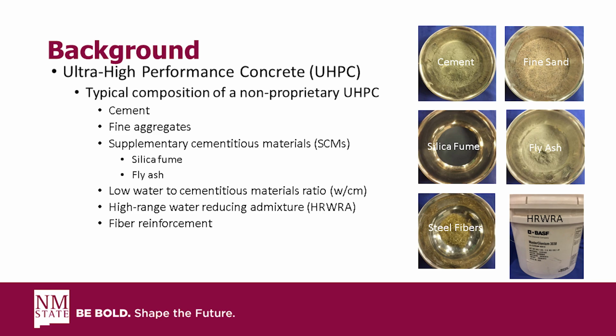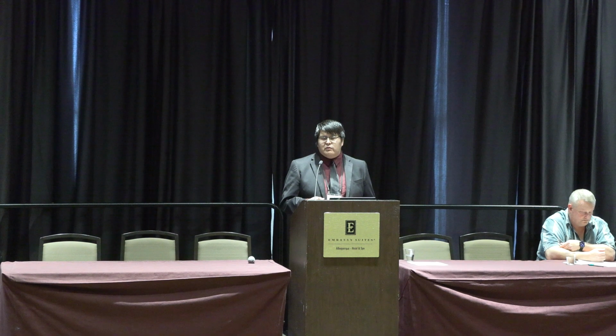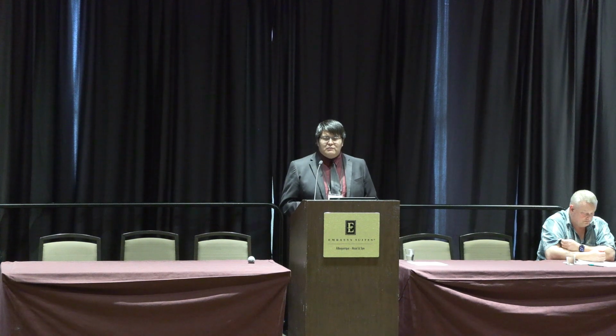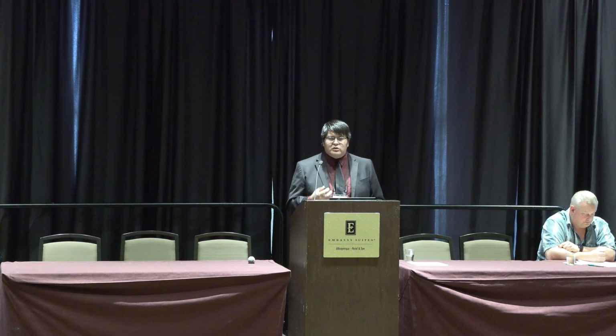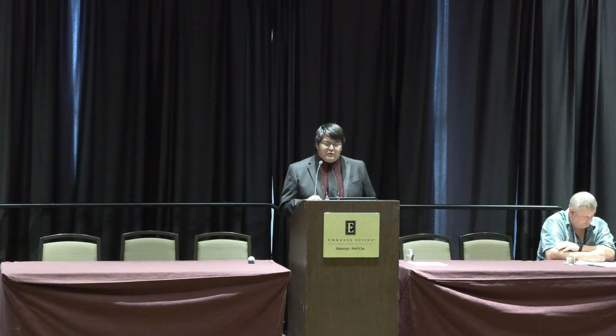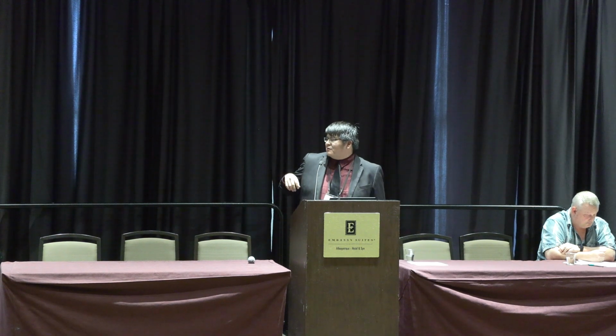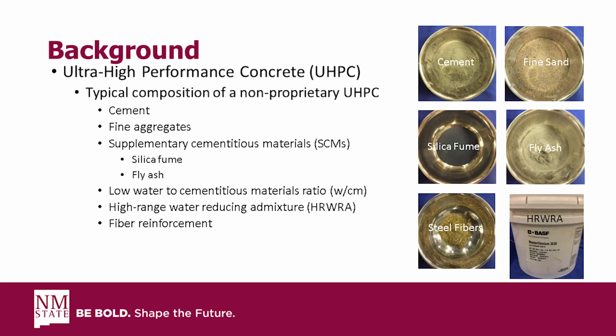Okay, and we have a low water to cementitious materials ratio, typically around 0.13 to about 0.16 is what we're looking at. And to have that low of a water to cementitious materials ratio, we need to implement a high range water reducing admixture, or a superplasticizer. In this case, we're using the MasterGlenium 3030 superplasticizer, which you can see the container of in the bottom right photograph.